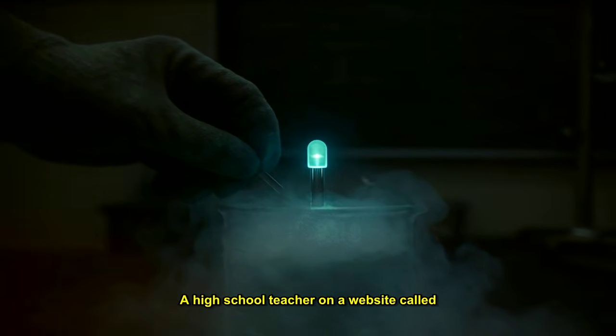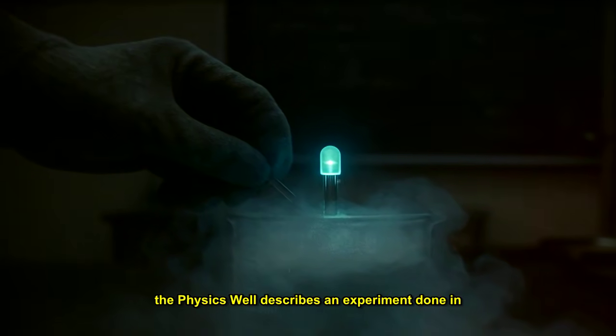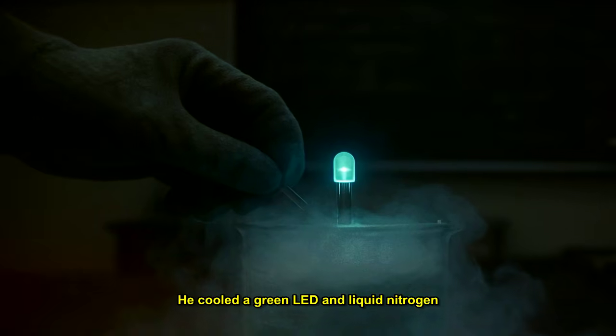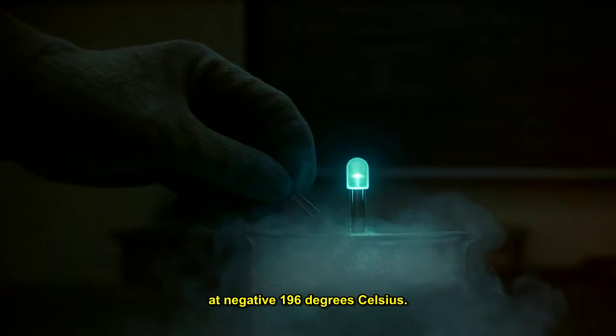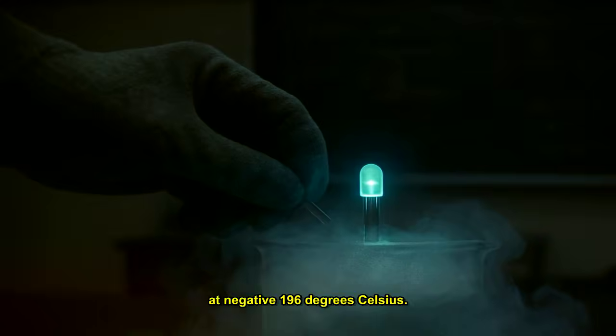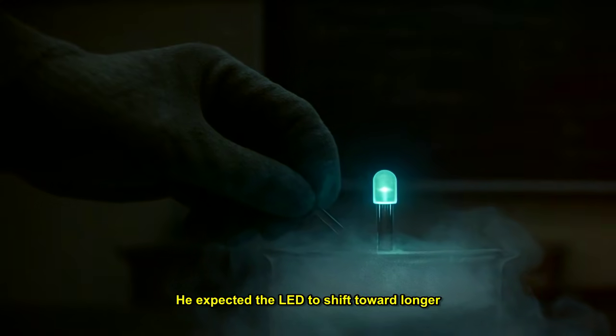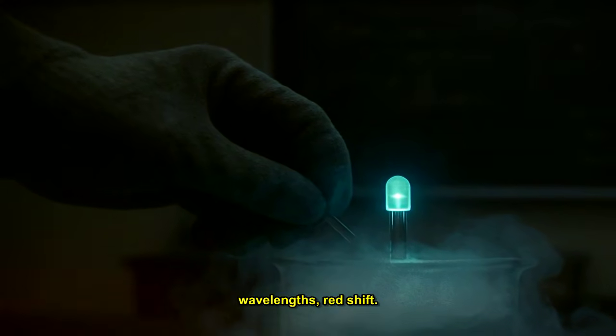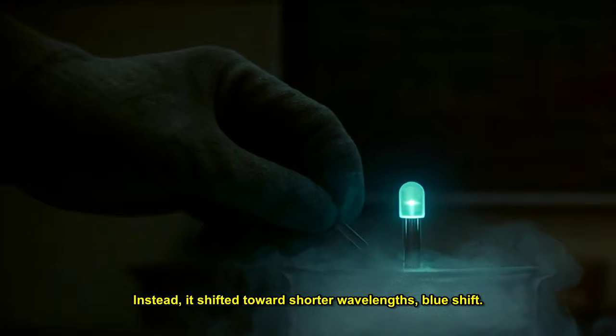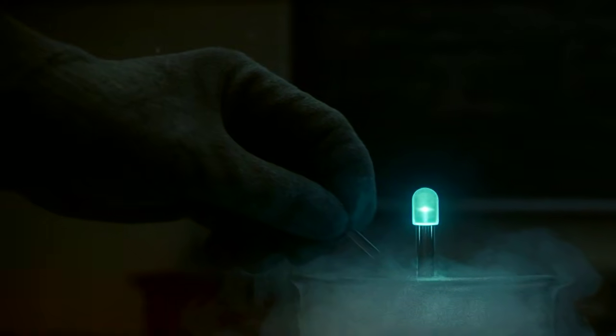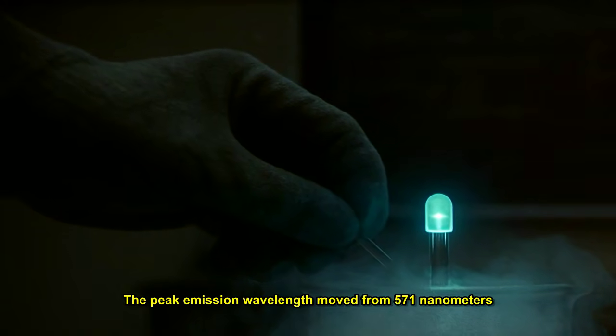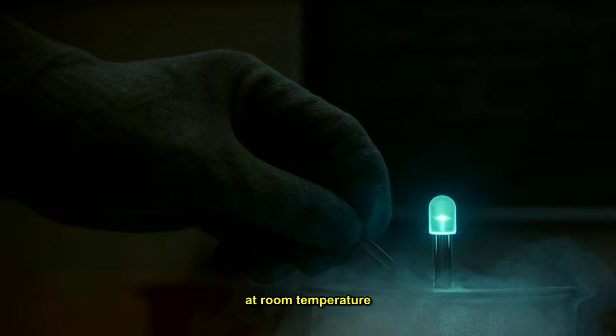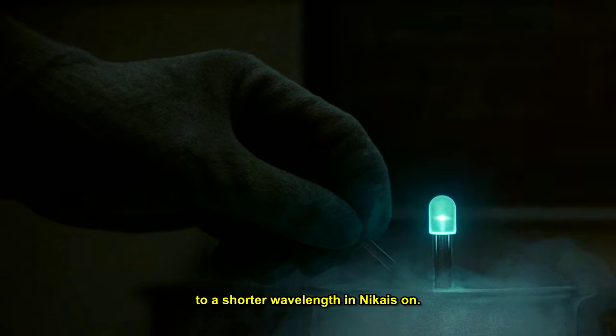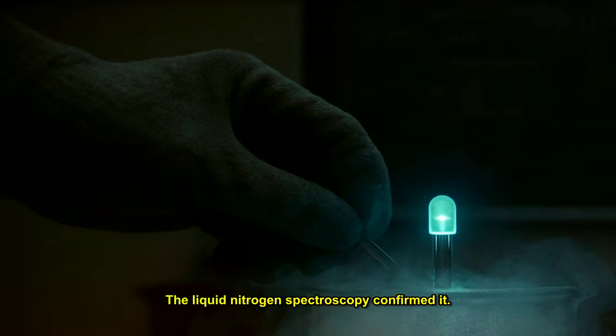A high school teacher on a website called The Physics Well describes an experiment done in his classroom. He cooled a green LED in liquid nitrogen at negative 196 degrees Celsius. He expected the LED to shift toward longer wavelengths, a red shift. Instead, it shifted toward shorter wavelengths, a blue shift. The peak emission wavelength moved from 571 nanometers at room temperature to a shorter wavelength in liquid nitrogen, and spectroscopy confirmed it. The color shifted from green-yellow toward blue-green.